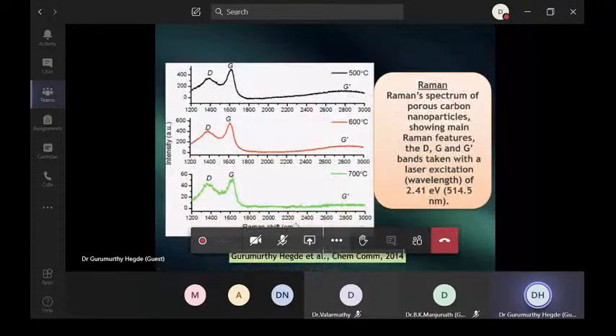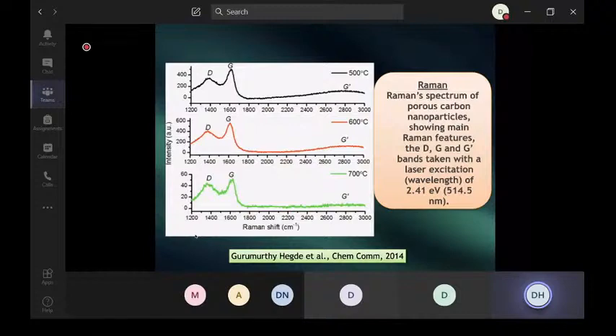That means your material is carbon going towards graphitic, which has been evident from the FTIR, that you are getting C double bond C peaks, which is characteristic of the graphene material. Then we again subjected to Raman spectra, and Raman spectra again showed the characteristic D, G, and G prime, which is the nature of the porous carbon nanoparticles, where you can see the Raman features here.